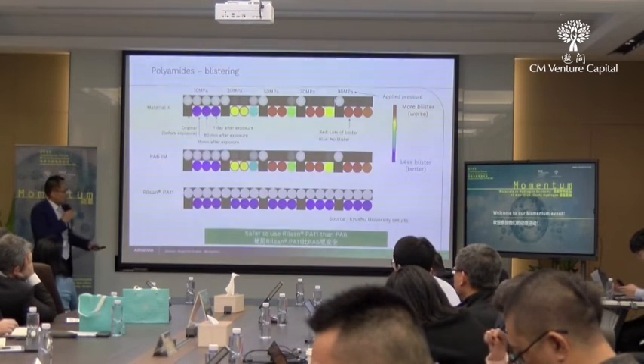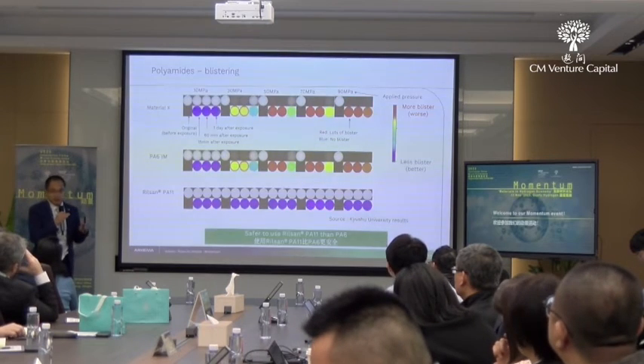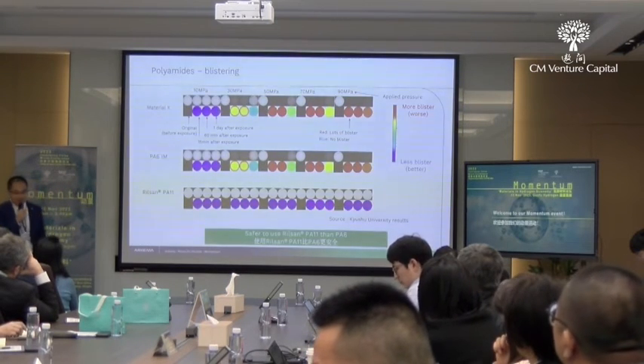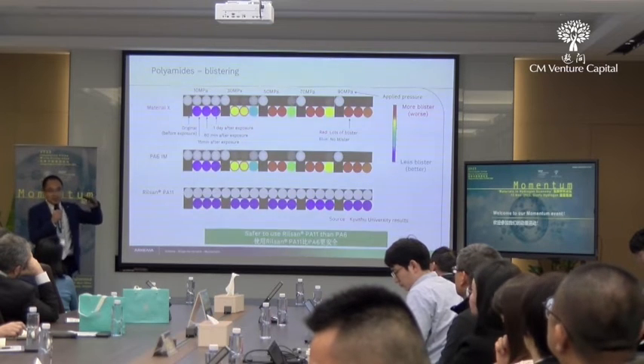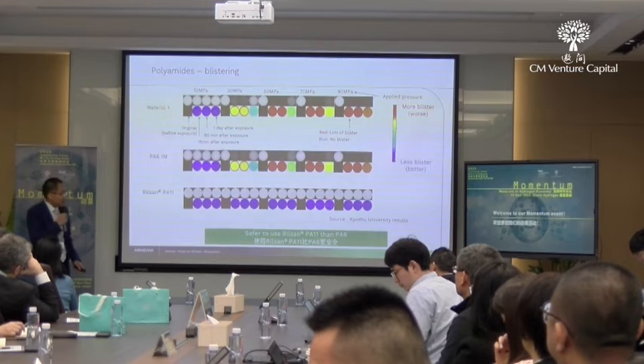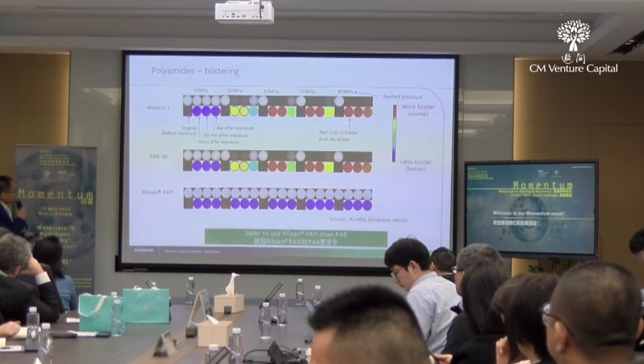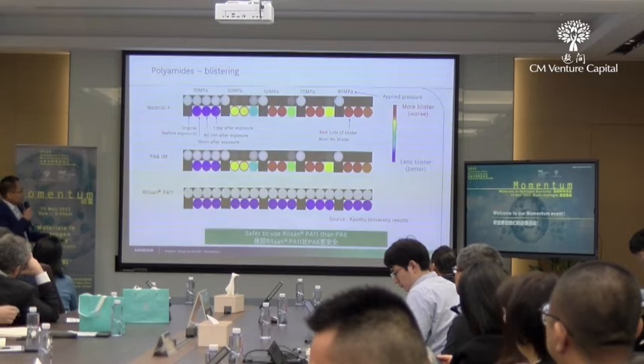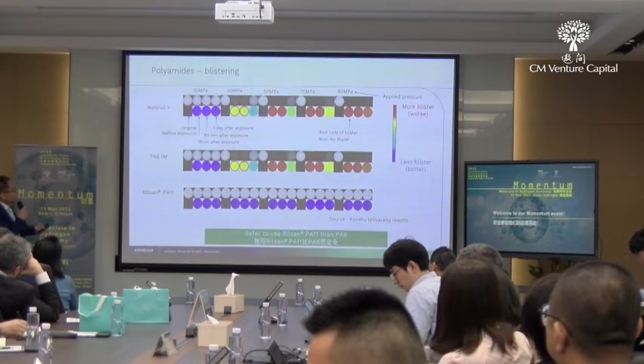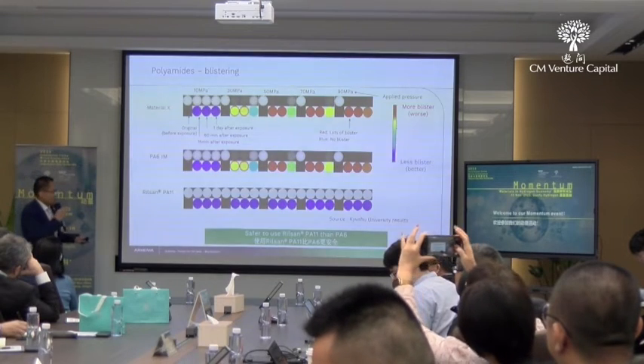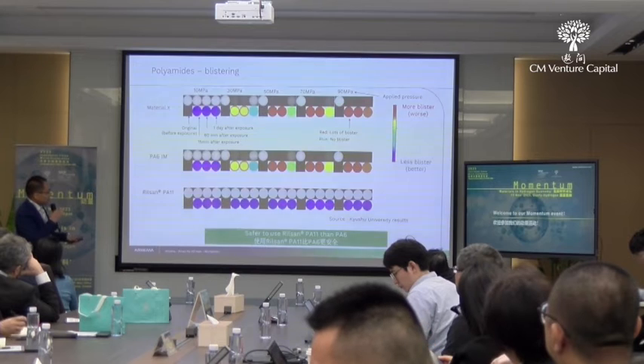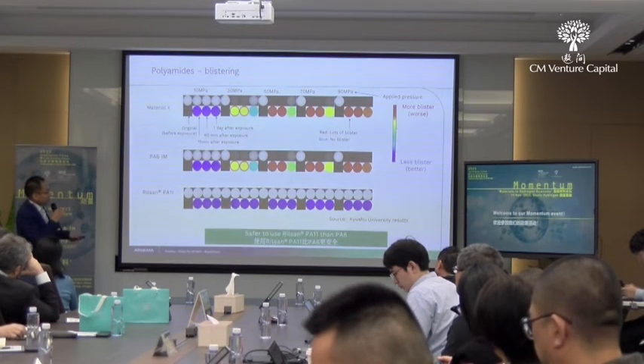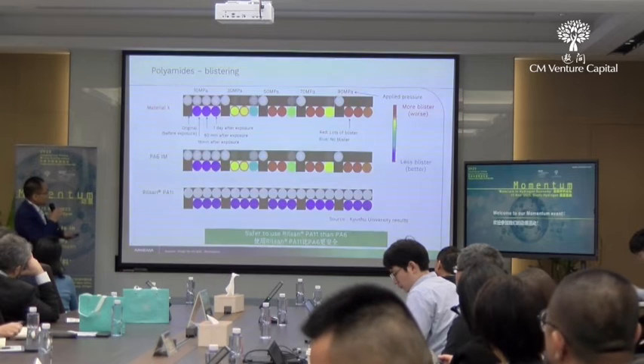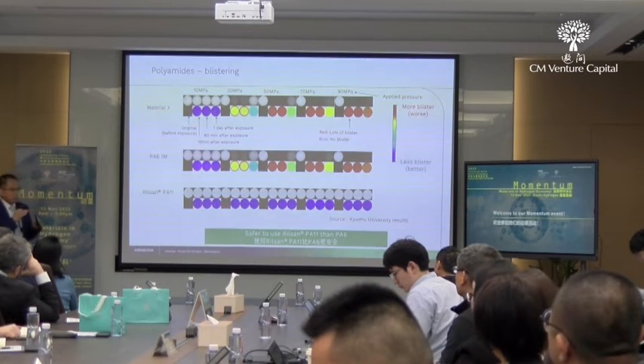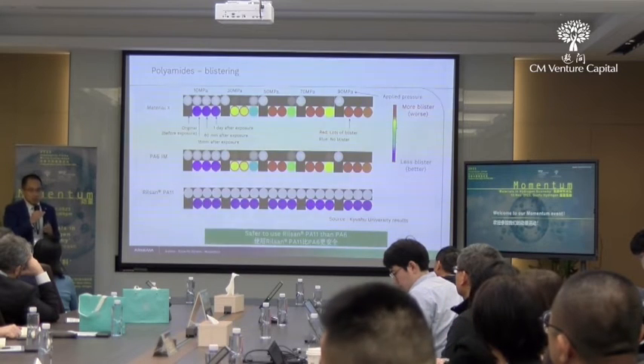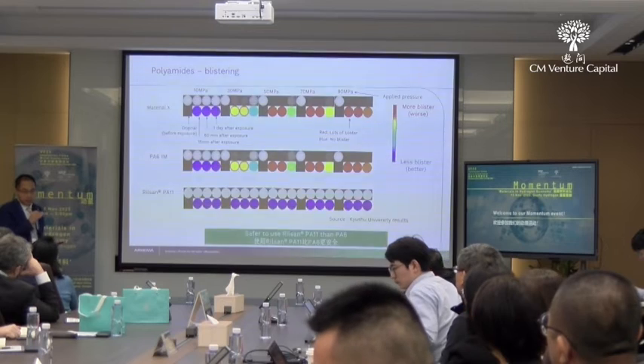I will show you our studies with Kyushu University. I think some of you may have heard of this university. More likely the top level of hydrogen studies in the world. So this is the comparison between the PA6 and PA11. You can see PA11 can survive from 10 megapascal to 90 megapascal. We didn't see too much blistering, like you see the blue ones have less blistering, and the red ones have more blistering. So we believe that PA11 can stay much safer compared with the PA6.